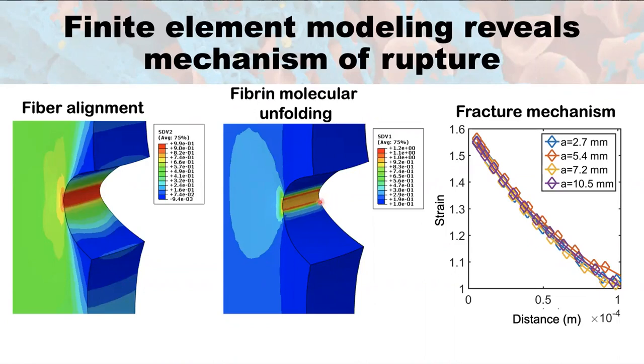So it's able to show us where there would be molecular unfolding, again, with most of the unfolding happening in those red and orange regions immediately ahead of the crack tip. It's able to output the strain as a function of the distance from the crack tip with respect to different crack lengths represented here as A. And as you can see, that function of strain to distance from the crack tip overlays between all of the samples with different crack lengths. Again, pointing to the fact that this is a material property of the fibrin network.